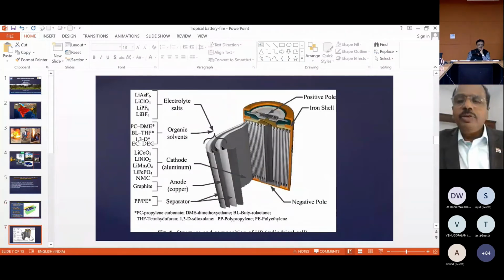And if you see the battery, why lithium-ion batteries are different from lead acid or nickel metal hydride or any primary cells we know. All the cells we know are aqueous batteries. So you have only a water-based electrolyte, which is not going to blow up. But in lithium-ion batteries, the electrolyte is essentially EC and DEC, ethylene carbonate and diethyl carbonate, which are organic solvents, which are like petrol and diesel. If you have a little bit of hot spot, they just get evaporated, and if the temperature rises further, then it will blow, like a bomb.